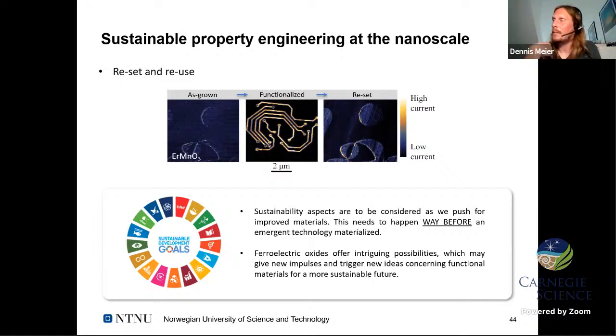So when I have now my domain pattern in the manganites and I would like to switch it, you really have to go to low temperatures and apply huge electric fields so that you even switch the system, because we are acting on the improper, the secondary order parameter, and you have to kind of drag the structural change along with you. So they are extremely stable, and you have to apply at least one order of magnitude higher electric fields than what we are working with when we play with the conductivity. Oh, okay, great. So the activation of the currents and the movement of the domain walls are really far apart.